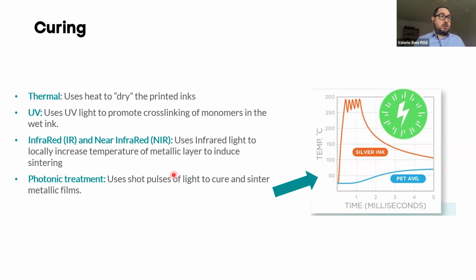But some of the inks require curing at higher temperatures in order to increase their properties, especially when we talk about electrical properties. And this could be infrared or near infrared or photonic treatment. So these are all treatments that use high energy light to heat up locally the inks, in order to increase their properties.